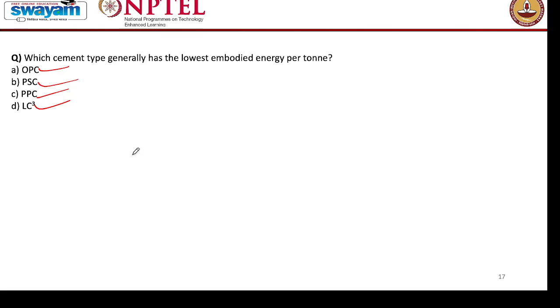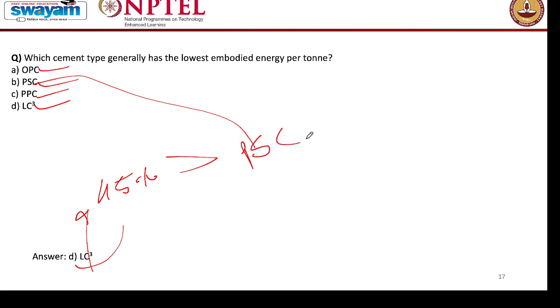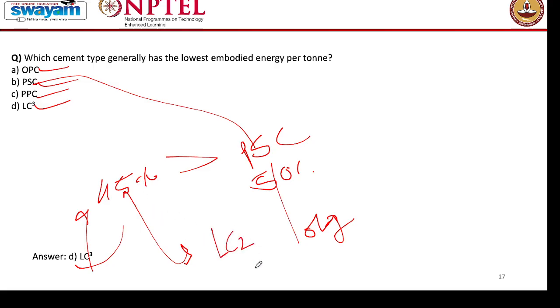Okay, let's try to solve the answer. LC3. Why? Because in LC3 we have 45% replacement of clinker, right? Which reduces the CO2 footprint drastically. Then there is PSC. In PSC also we replace by up to about 50% with slag, right? However, here the temperature requirement for production of LC3 is lower.